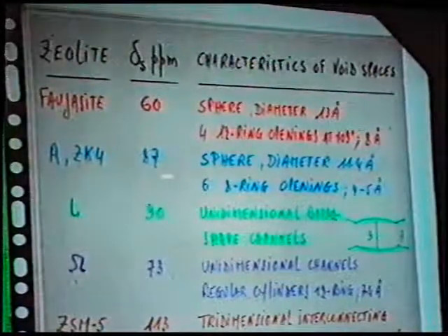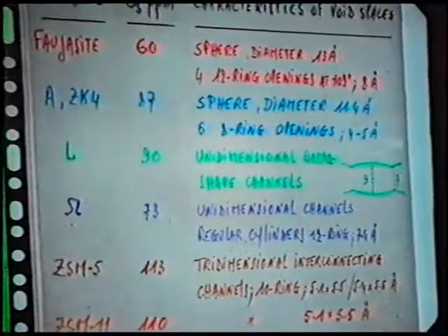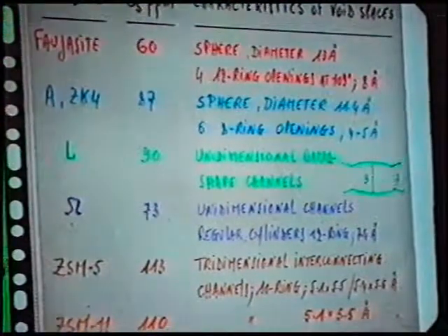We see also that we may have roughly the same chemical shift for different structures. So the relationship between the chemical shift and the structure is difficult to define because the chemical shift at zero concentration depends on the structure of the void space, on the dimension of the channels and cavities, and on the ease of diffusion of xenon inside this free space.